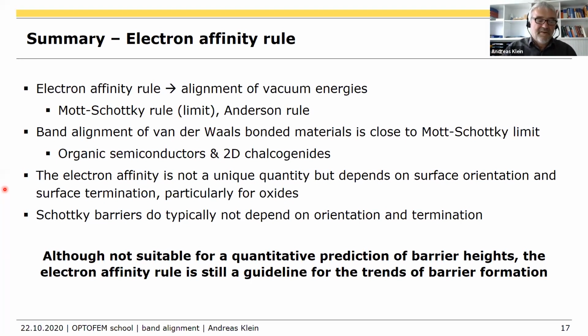We very often make interfaces of materials which are not epitaxial, so they are strongly lattice mismatched. So there must be a lot of dislocations at the interface. And I would say we don't see much influence of this kind of thing on the interfaces, because what we are trying to do is move the Fermi level as high as possible and as low as possible. And if this is possible with non-epitaxial interfaces, it means that we do not have Fermi level pinning. I guess that would be quite a good answer for this.